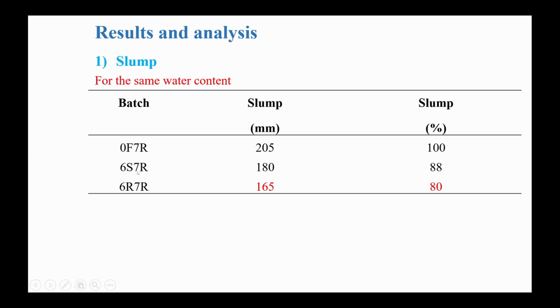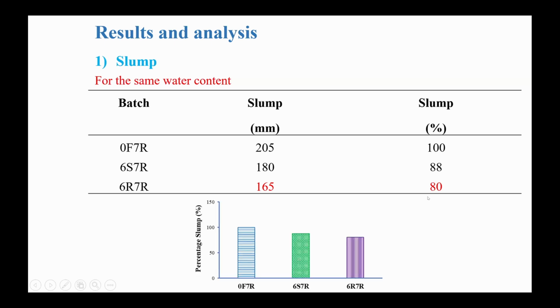Here the 6S represents the 0.6% of the industrial steel fibers, and 6R represents 0.6% of the recycled steel fibers. That is from the waste tyres. So you can see that there was a significant effect of 0.6% of the recycled steel fibers, and the slump was decreased by 20% as compared to the plain concrete without fibers.